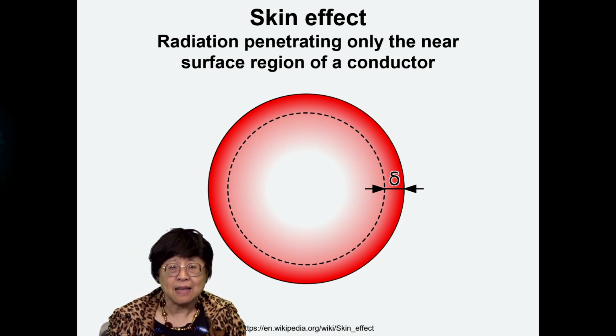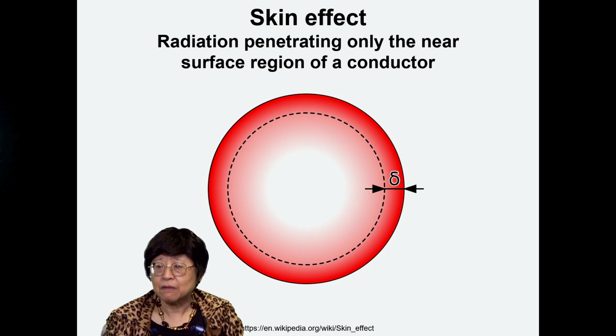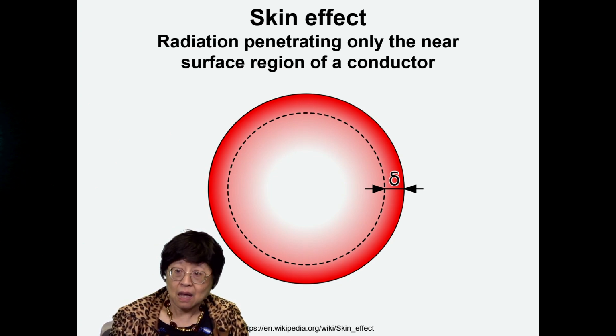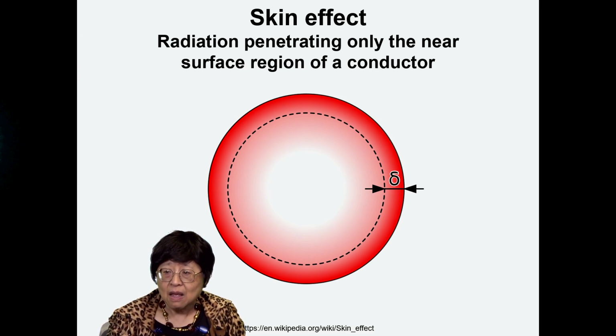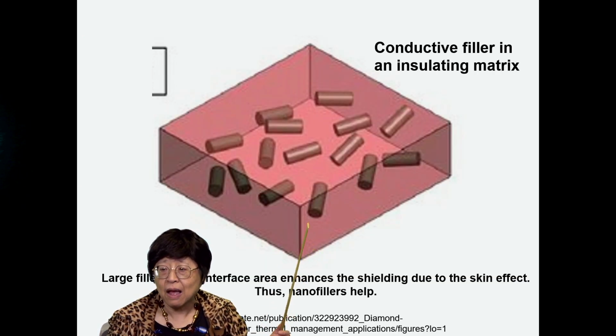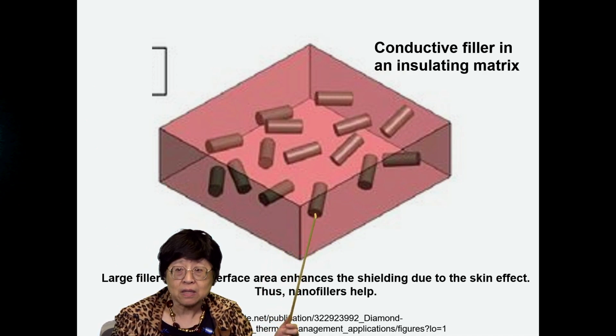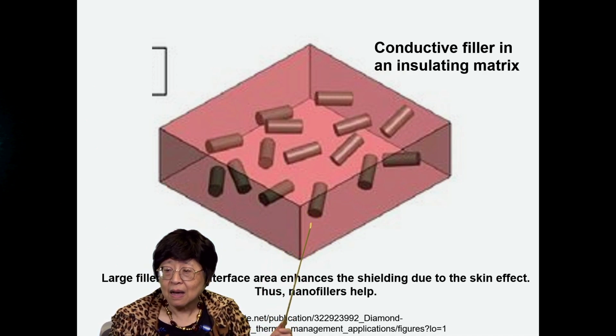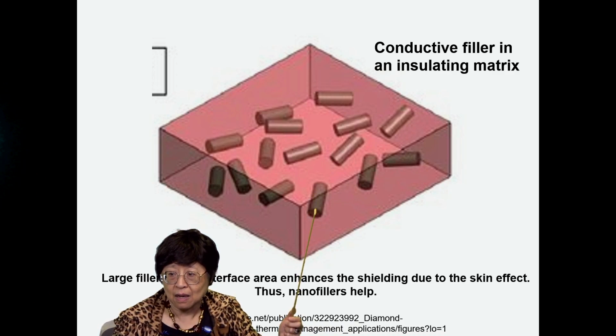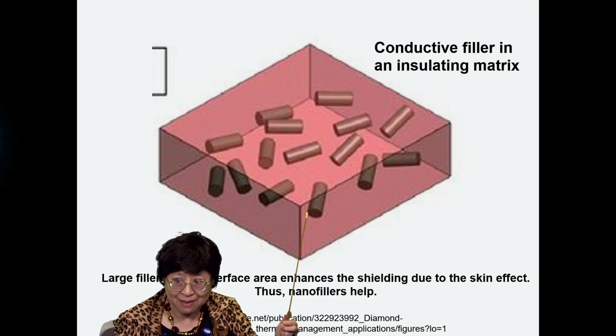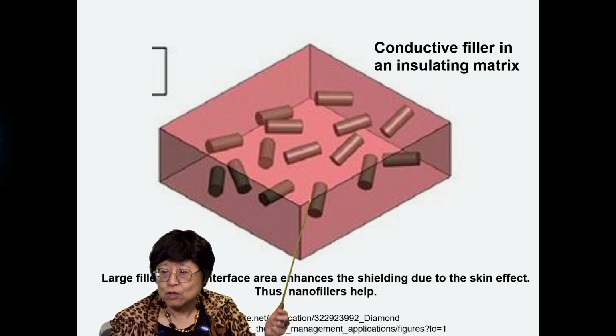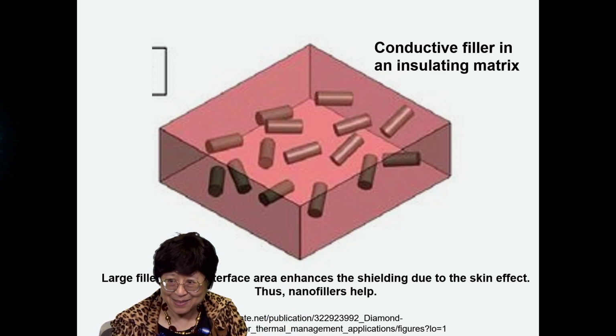Why are these tiny diameters so important? Well, it's because of the skin effect, which pertains to the radiation penetrating only near the surface of the conductor. See, only the surface region sees the radiation. So if you have a non-conductive matrix and you have in it some conductive filler, whether particles or fibers, the radiation can only penetrate the near surface region of each unit of the filler. And so the inside region of each filler unit is sitting there doing nothing. So it'd be better off if each filler unit is very small in size.